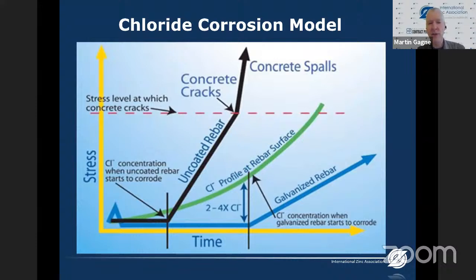This is anywhere from 2 to 4 times, and actually in some examples we see it's much higher, before the galvanizing starts to corrode. And it will corrode because that's its role, to protect the steel. But we can see the slope of the line for the galvanized rebar is much less than the slope of the line for the uncoated black rebar. And this is because the corrosion products on the galvanized rebar do not exert the same stress on the concrete.